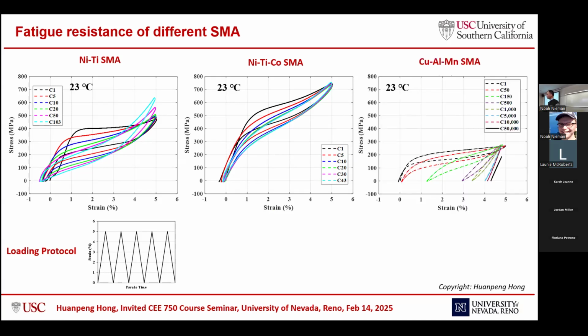Here comes the copper aluminum manganese shape memory alloy. This is really impressive because even though this material has really low yield stress, it withstands 50,000 cycles of 5% strain. This is really, really impressive. This definitely exceeds the demands for earthquake engineering, and may be better suited for other vibration control dampers.